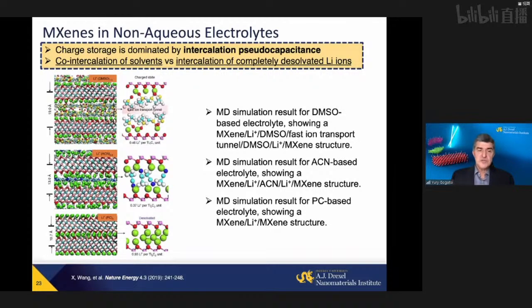In the case of acetonitrile, lithium ions go to the surface of MXene, but solvent molecules separate layers, hurting electronic transport, also taking space and leading to breathing of the electrode, expansion and contraction. But in the case of PC, there is a complete desolvation and lithium ions go between the layers without solvent, giving more energy stored, larger charge storage, but also no change in the spacing as we cycle the electrodes.